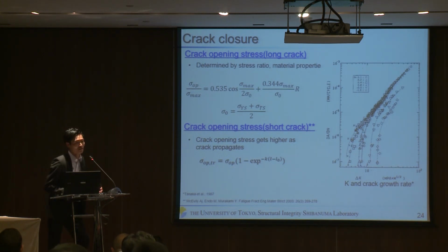Okay, so next, crack closure. Fatigue life is said to be affected by crack closure, so the effect of crack closure is considered. For a long crack, the effect of crack closure is constant, as shown in this equation. But for a short crack, the opening stress changes, so this equation is employed to consider the change.